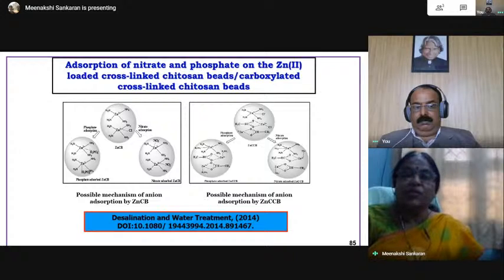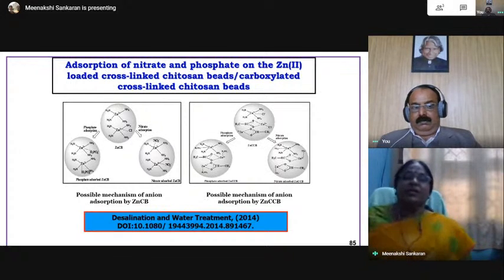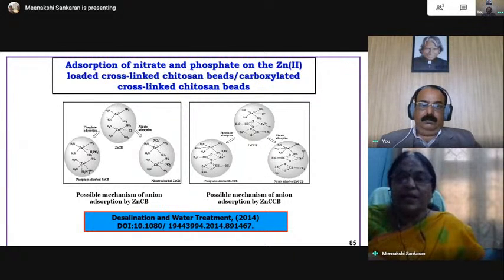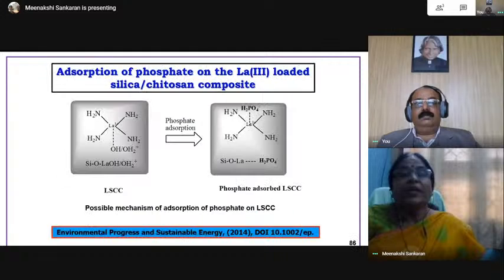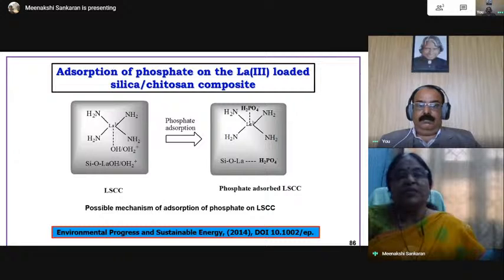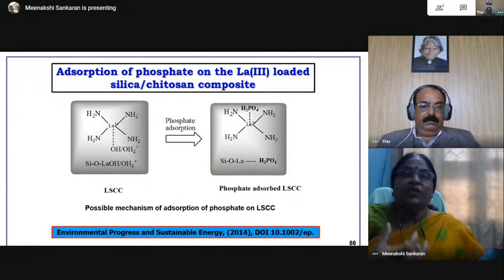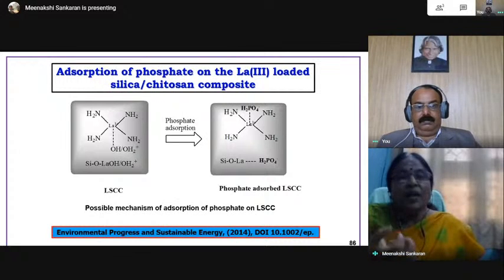And here is the adsorption of nitrate and phosphate using zinc loaded cross-linked chitosan beads and carboxylated cross-linked chitosan beads. By means of ion exchange, nitrate has been removed. By means of complexation, phosphate has been removed. And there is lanthanum loaded silica chitosan composite. Here we have made a composite of silica with chitosan, and when we wash with an alkali, silica will come out and it will create voids in the composite. Those voids, those pores, will keep some nitrate and phosphate also. So this material is also capable of removing nitrate and phosphate.